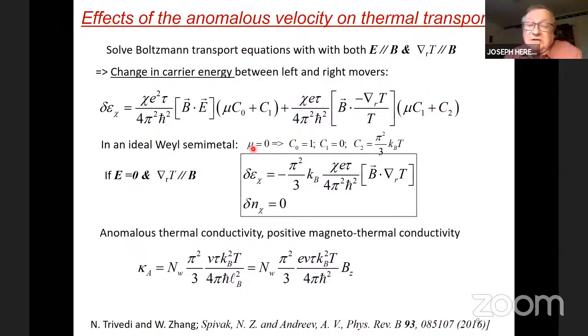If we now do this in the ideal Weyl semimetal, mu equals zero, then C0 is one, but mu C0 is still zero. This is zero, this is zero, this is zero, but C2 is not zero. That Fermi integral in degenerate statistics becomes pi squared over three times kBT. So what we have now is no change in carrier concentration between the left and the right movers, but a change in energy that is proportional to B dot grad T, and is given by pretty much the same type of parameters, the inter-Weyl point scattering time. And so we can take a look now at an anomalous thermal conductivity, which has pretty much the same form as the anomalous electrical conductivity, and is proportional to the magnetic field applied parallel to the temperature gradient.